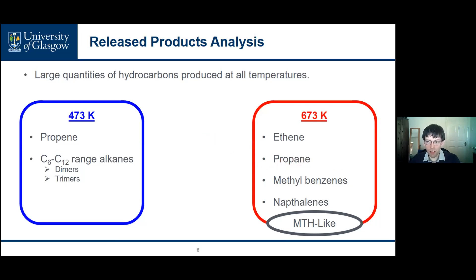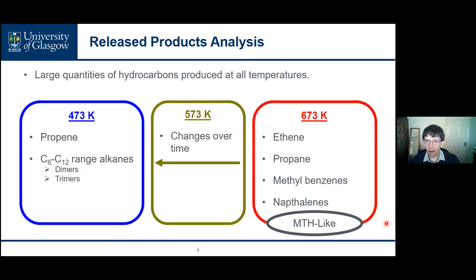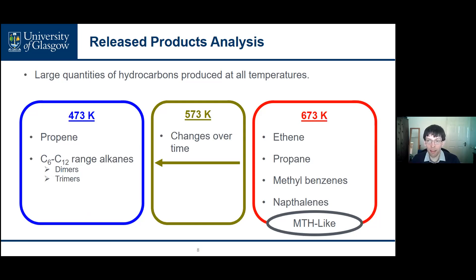The reaction at 573 K, as would be expected, lies between these extremes. It starts out operating quite similarly to the reaction at 673 K with slightly different product ratios, but over time starts to shift towards the less aromatic, more alkane-heavy product slate closer to that found at the lower temperature. This process is not anywhere near completion after the reaction time used and is still ongoing at the point where we removed the samples for ex situ analysis.